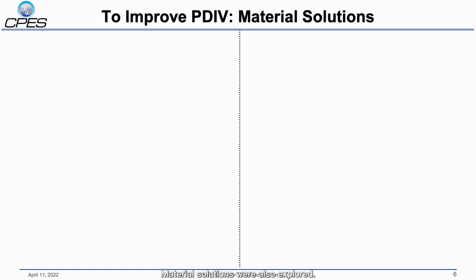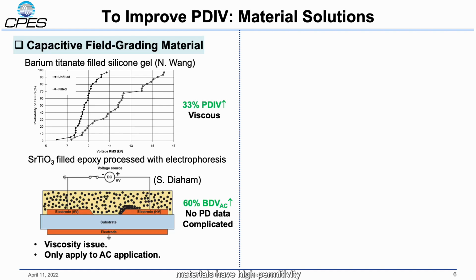Material solutions were also explored. Researchers are focusing on two groups of the materials. The first group of the materials have high permittivity. They are called capacitive field grading material. For example, barium titanate was filled in the silicone gel to increase the permittivity of the silicone gel. It was reported that this material can increase the PDIV of the DBC substrate by about 30%.